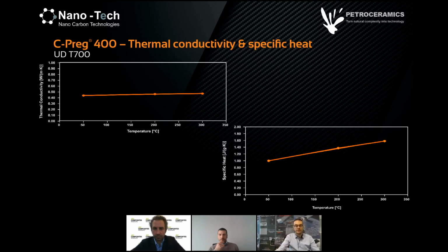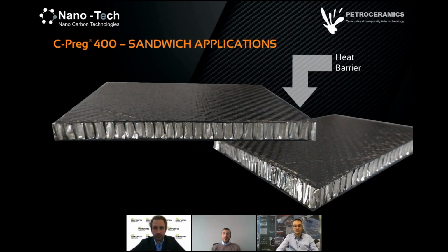So Andrea showed the very good flammability properties, the very good fire properties, the very good resistance to heat. And besides, the thermal conductivity and the specific heat of our composite are aligned with those of standard polymer-matrix composites. So this is very good, and thanks to the thermal properties and the thermal stability, Cpreg 400 is particularly suitable for heat-resistant thermal barriers alone or in sandwich structures. And in particular, it is very easy to join the prepreg with aluminum honeycombs.